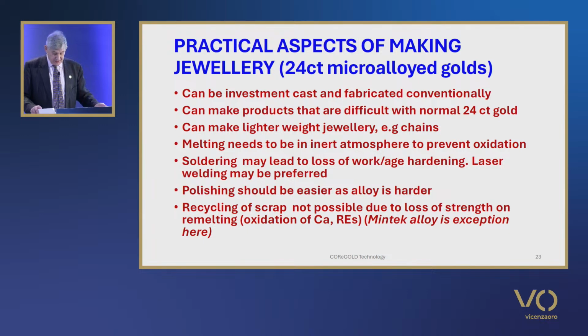Melting generally needs to be done in an inert atmosphere to prevent oxidation of the microalloying metals. Therefore, they cannot be made easily in a small workshop situation by conventional melting in air. As with normal 24-karat gold, soldering must be consistent with local national laws, and in some countries, use of a lower 22-karat solders is allowed, although there may be limits on the amount of solder used.